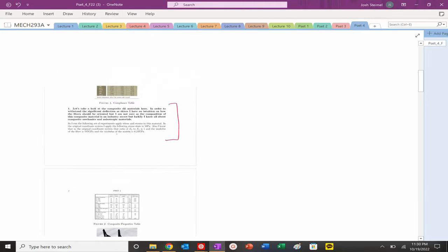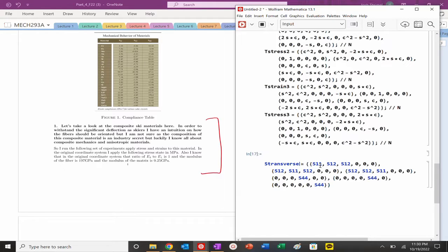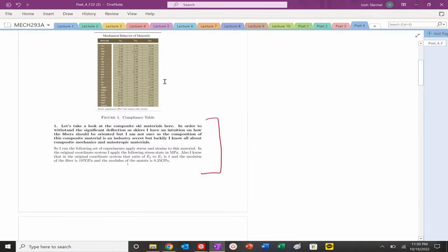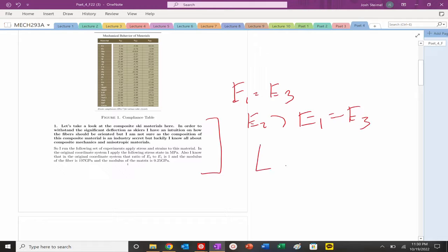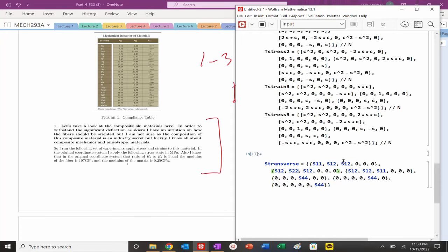Let's zoom out and define some values. If E3 equals E1, then S33 should equal S11, while S22 is different. Since E3 and E1 are equal, the fiber is placed in the 2-direction. It's helpful to draw your coordinate system and fibers to see where unique planes exist. Here the 1-3 plane is the unique plane.